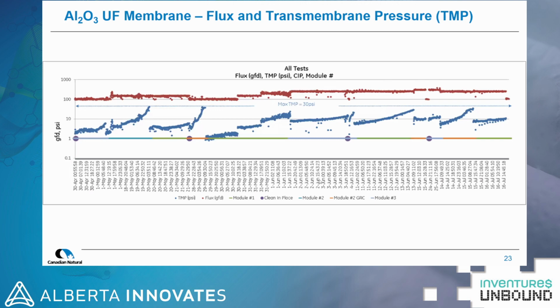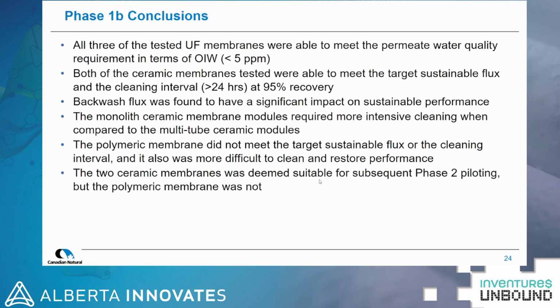So based on our piloting, the conclusions were that all of the UF membranes, ultrafilter membranes, were able to meet our permeate water quality in terms of oil and water. Both the ceramic membranes were able to meet the target flux and the cleaning interval at a 95% recovery. It was found the backwash flux was a key parameter to maintain sustainable performance. The monolith ceramic took a bit more to clean compared to the multi-tube ceramic elements. The polymeric membrane didn't meet our target flux or cleaning interval, and it was more difficult to clean as well. So the most significant finding from this pilot was that both the ceramic membranes were suitable for the subsequent phase two piloting, but the polymeric membrane was not.